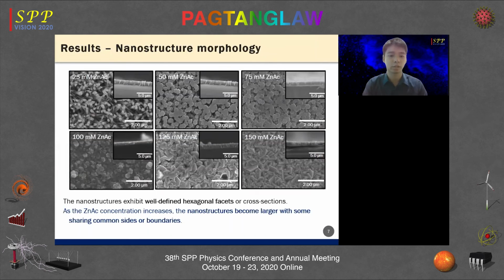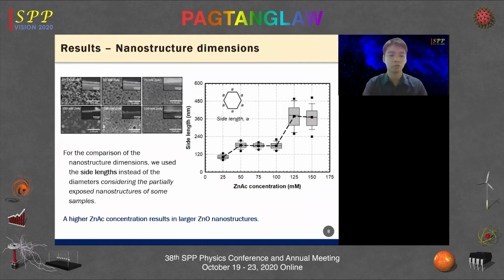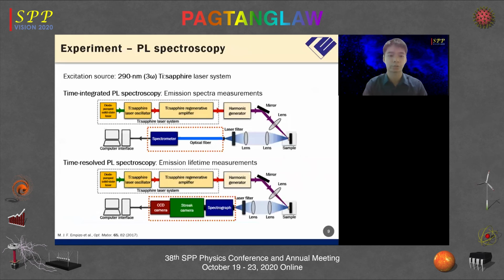Now this slide shows the SEM images of the hydrothermal grown zinc oxide nanostructures. All of these exhibit well-defined hexagonal facets or cross-sections. As the zinc acetate concentration increases, the nanostructures become larger, with some sharing common sides or boundaries, or even coalesce to form larger structures. For the comparison of the nanostructure dimensions, we use the side lengths instead of the diameters, considering the partially exposed nanostructures of some samples. As we can see here, a higher zinc acetate concentration results in larger zinc oxide nanostructures.